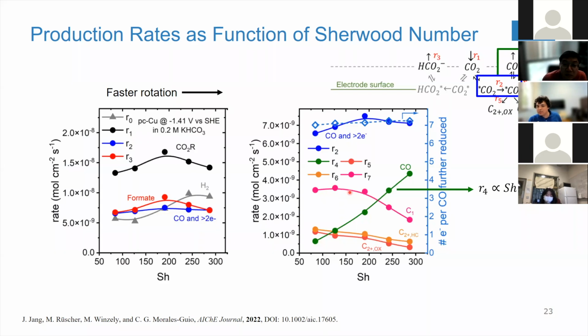And we have enough evidence to suggest that the pathway for the production of ethylene and methane is the same. They share a common reaction intermediate, and then they split, depending on the kinetics, on the relative rates of a thermal step, which is the CC coupling, versus an electrochemical step, which is the addition of protons and electrons to a carbon atom on the surface of the electrode.